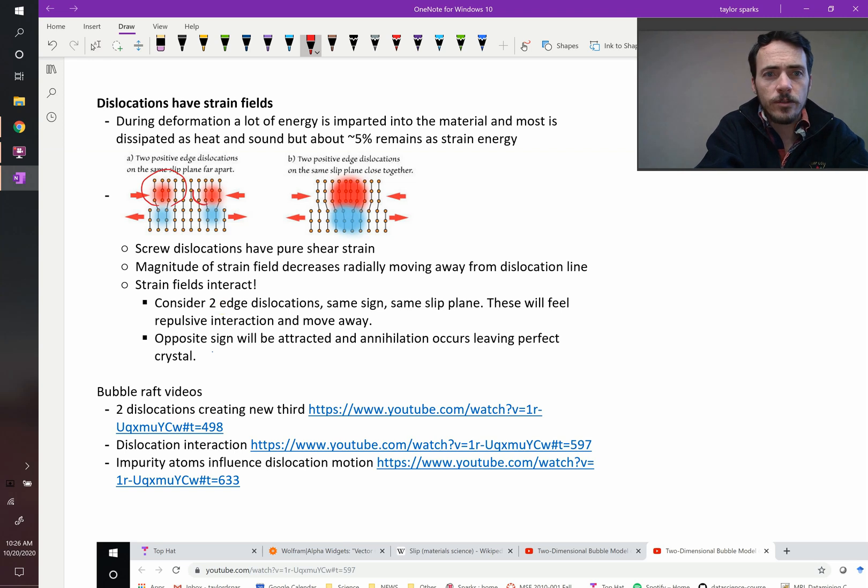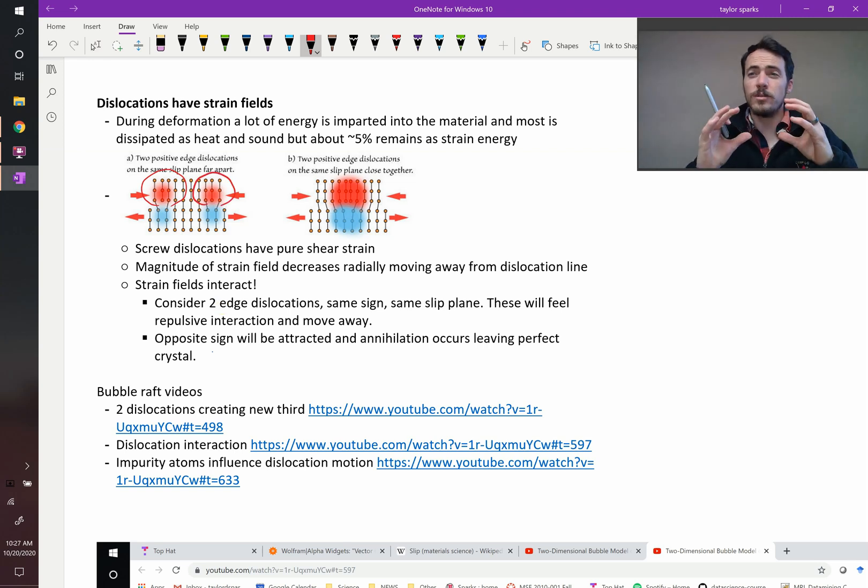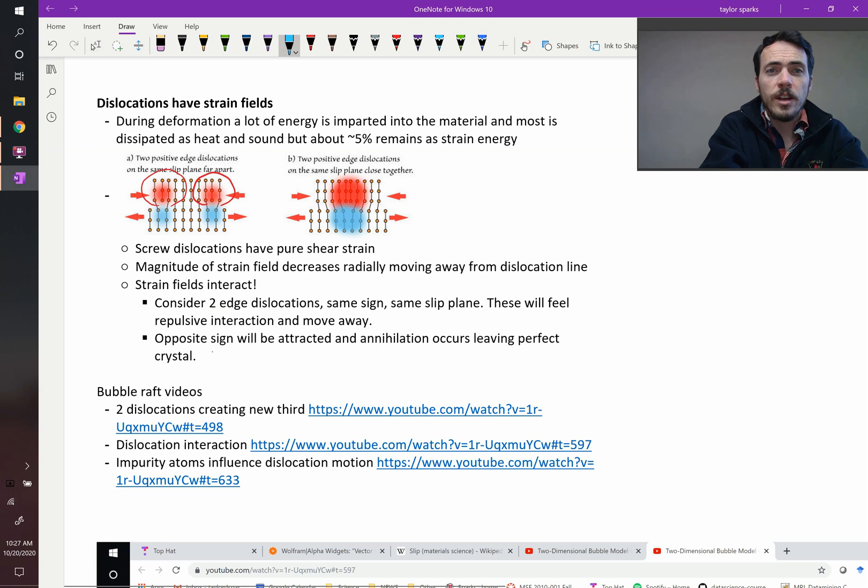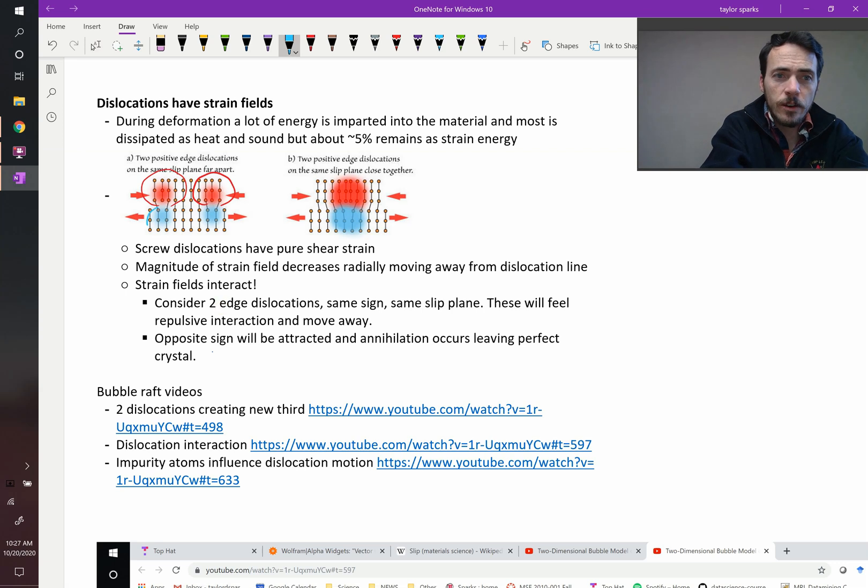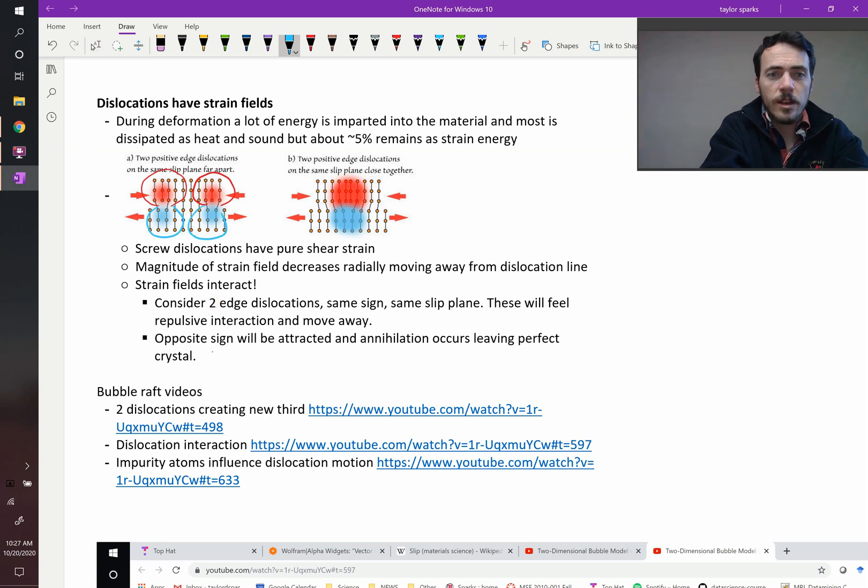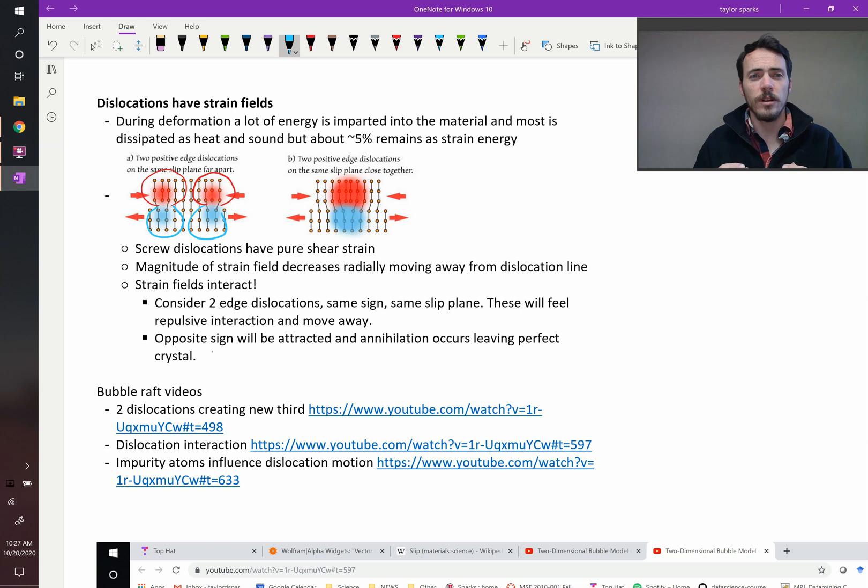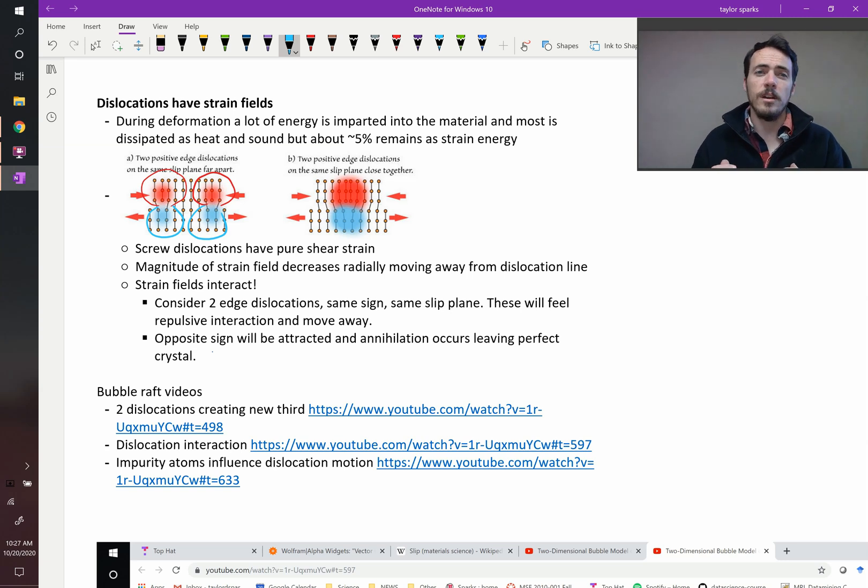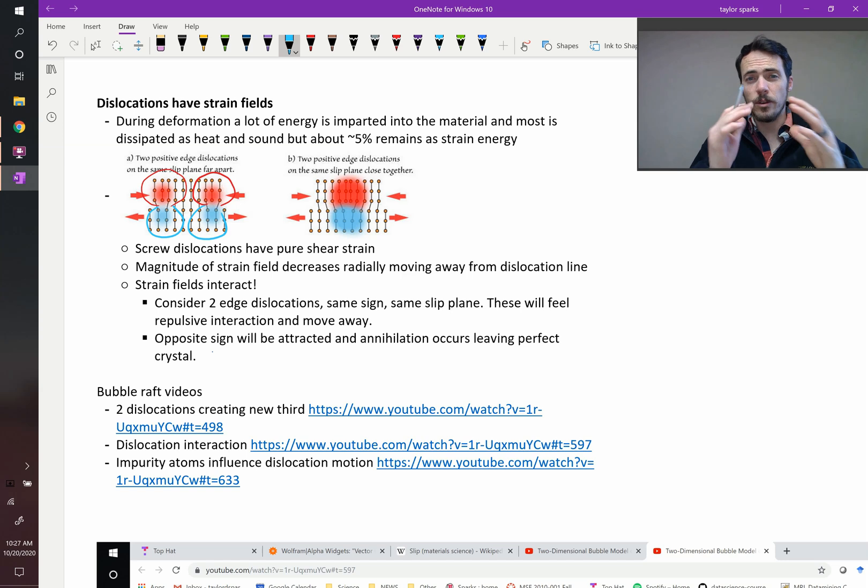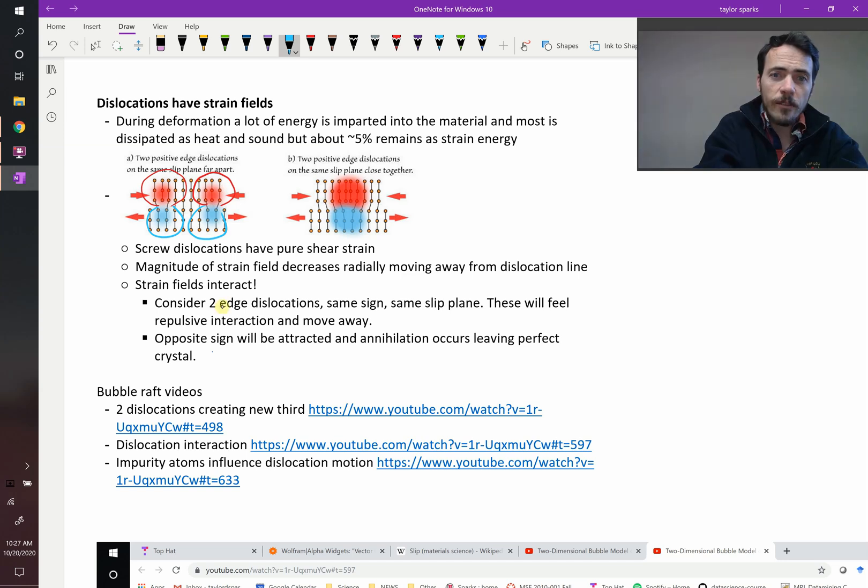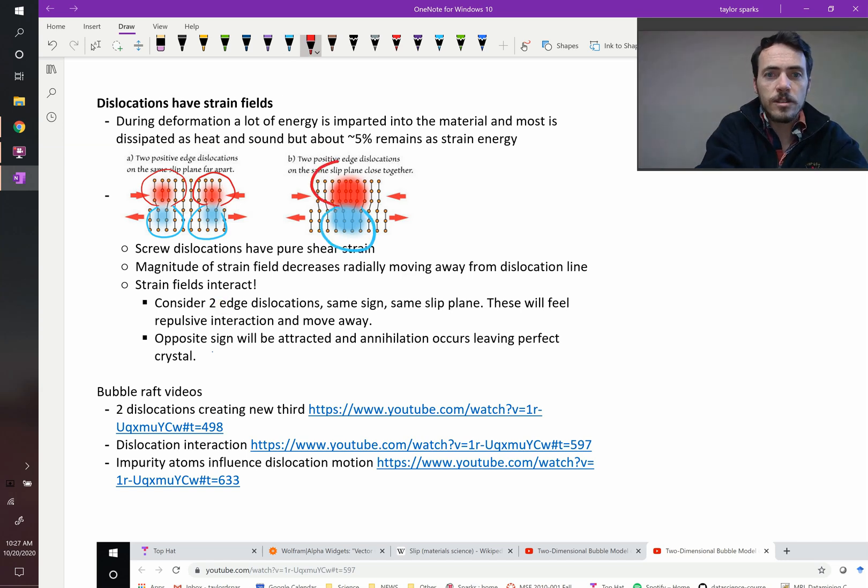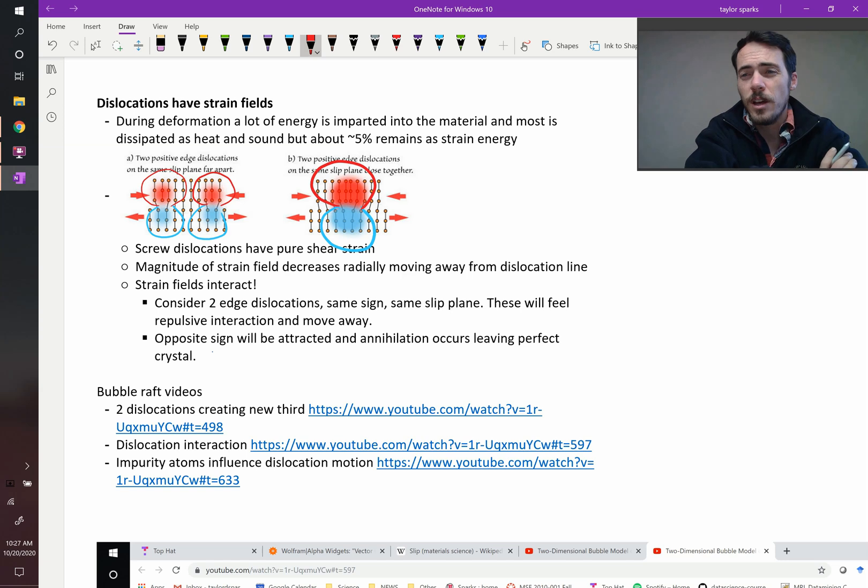So if you have two of these things next to each other, those compressive stress regions are close to each other. And underneath the dislocation, you're going to have tensile regions. So again, if these things are right next to each other, then they're going to be at the same sign. So imagine what would happen. If these things came together, then you're going to have a really severe tensile region and a really severe compressive region. That's not going to happen.